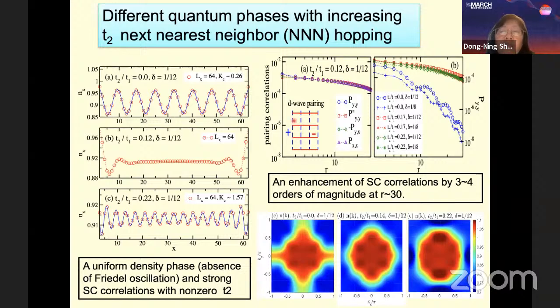We find that if 2 bonds are both along the y direction, we always get a pairing correlation which is positive. But if one pairing is along the x direction, the pairing correlation is negative, which is consistent with D-wave pairing symmetry. We also compare the pairing correlation.